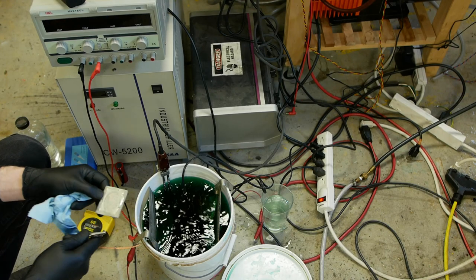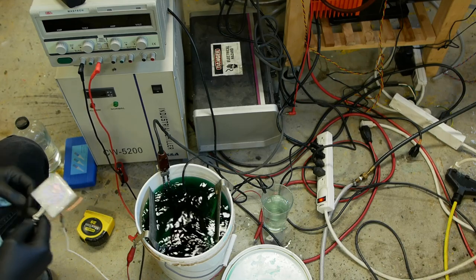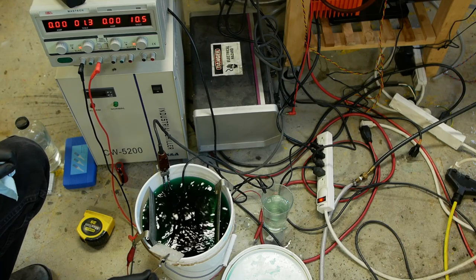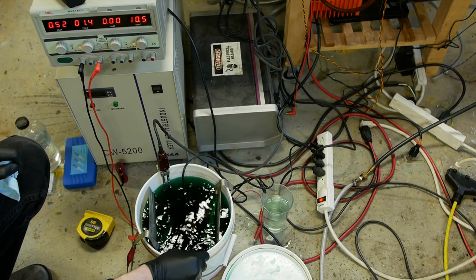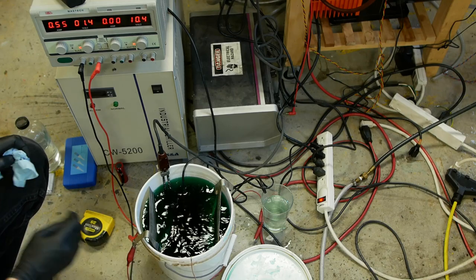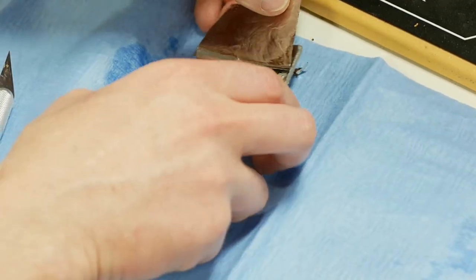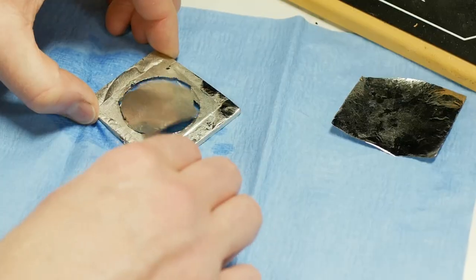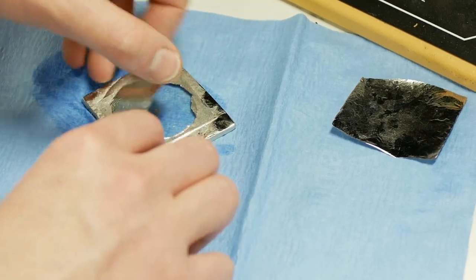Now that the thing is coated in silver, we can build up the bulk with an electrochemical process because now the whole thing is conductive. So I happen to have this nickel plating kit in my garage, and I hooked it up and deposited nickel on there for about an hour, which builds up a relatively thick layer. I mean, it's still thin, maybe about 20 or 30 micron, maybe a little bit more, about a thou of an inch. But it's thick enough that we can actually peel it off of the mold, off of the hologram, and now we end up with a true metal master.